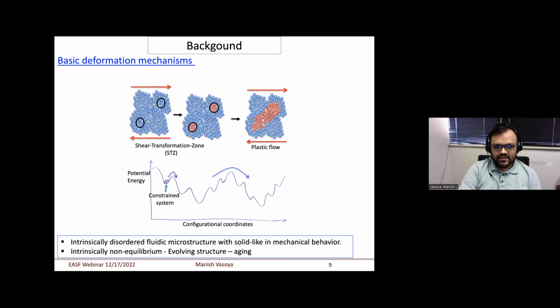So what is the basic deformation mechanism in this material? Because this is disordered, there is no structural defect like dislocations in metal. What people have introduced in the community as the basic mechanism of deformation is called the shear transformation zone. Within a cage, there are a few atoms that, upon loading, rearrange themselves and induce a local inelastic deformation. Here I'm showing a very schematic view.